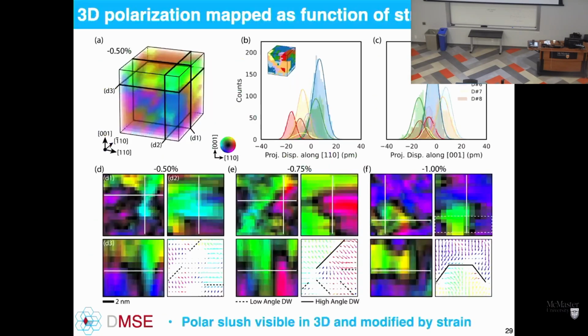All right, but let's zoom in here for a moment and look at just one of the data sets. In 3D, what you're seeing here is a map of different polar nanodomains and how they relate to each other in 3D. We can map out from that volume essentially the polar domains. That's the different colors, which would be the self-similar domains. And then we also have polar domain walls. These would be low-angle domain walls between different ferroelectric domains. We also find as we go up in higher strain, higher angle domain walls start to form. Here, even a head-to-head polar domain wall.